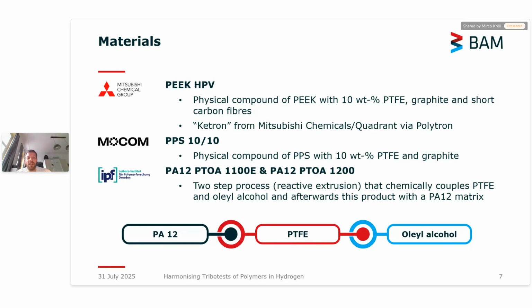So in the first step, you couple the oleyl alcohol, which is basically an oil, with the PTFE in a chemical way. After that, in a second step, you couple that oligomer to the polyamide 12 matrix. So it's not a physical compound, it's chemically coupled. There were two different compounds we tested. The difference here was the type of PTFE.